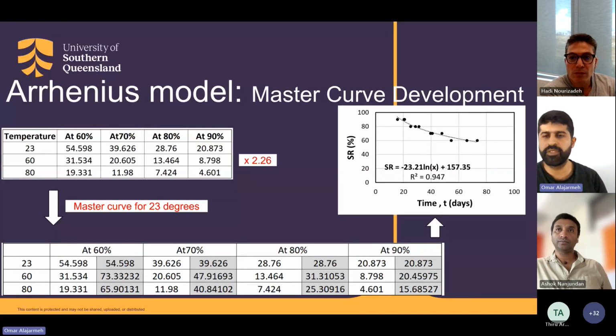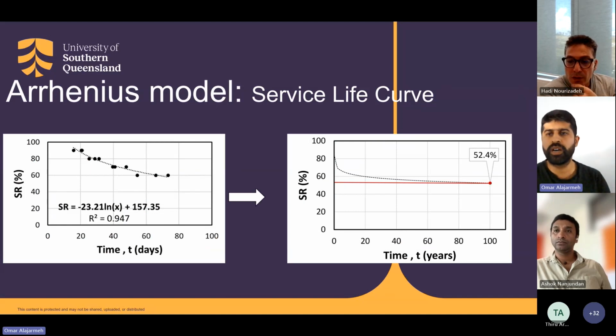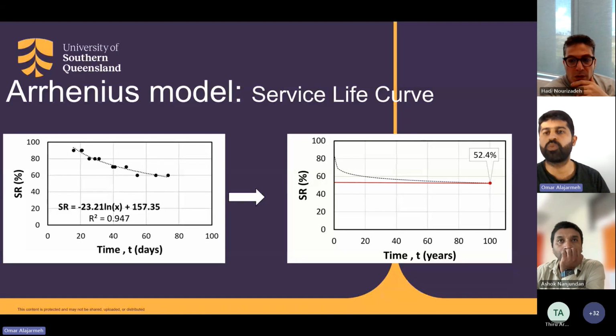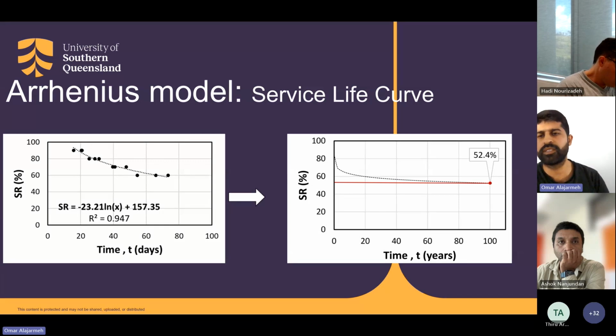Once I have that master curve, I take the function I get from the regression of those dot points, and correlate it to a service life up to the target years you are looking for. For example, in our project, it was a 100-year service life. How we do that is, you take the function and change the x values to get the y values. The strength retention after 100 years, in our case, was around 52%. That gives solid evidence on how those types of polymers react against environmental agents.